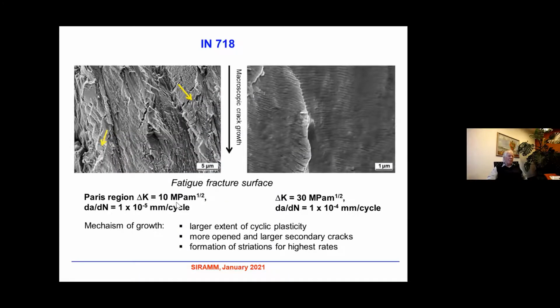On the other hand, in the Paris region, for delta K 10 megapascal, where the crack growth rate is nearly 10 to minus 5 millimeter per cycle, you can see that the fracture surface is much coarser, but a little bit similar to the threshold region. However, in the region of very high rates, for delta K 30 and crack growth rate 10 to minus 4 millimeter per cycle, we can see a larger extent of cyclic plasticity, more opened and larger secondary cracks. And we can even observe formation of striations. It means each cycle makes these striations. So it is very similar to the behavior of conventionally produced material.